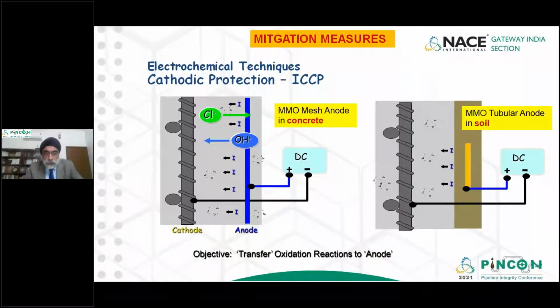Coming on to cathodic protection, as I said, there are two strategies. Either we put an MMO mesh anode in the concrete. So the blue color is an anode which is embedded in the concrete. On the right-hand side, we have an MMO tubular anode which is embedded in soil. The strategy of both the anodes is to deliver current uniformly onto the rebar.